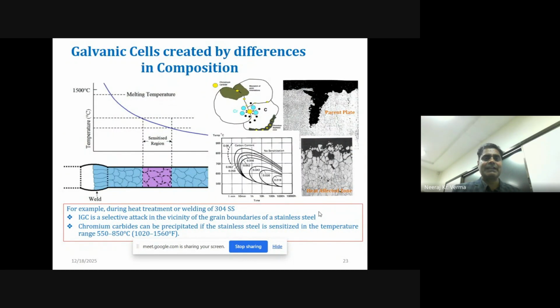Another good example where you can see these galvanic cells is in stainless steels. In stainless steels, what happens? Stainless steel has a tendency, if it is operated at a particular temperature, known as the sensitive temperature, to create a new phase. This new phase is chromium carbide, which settles down at the grain boundary, and it is a different phase with respect to the matrix. These are two different phases in the same system. Some phases will act as anodes and cathodes, so some cells start to form within the system. That creates a new type of corrosion known as IGC, intergranular corrosion.